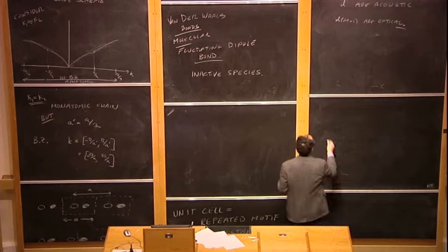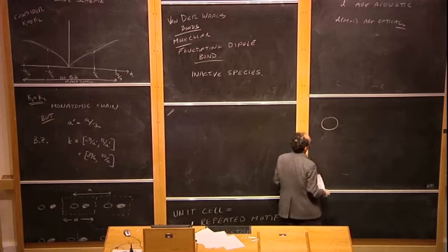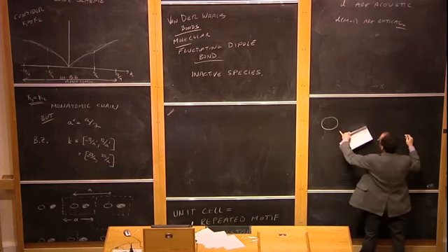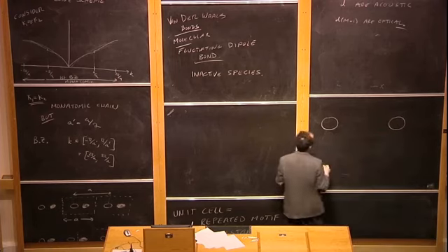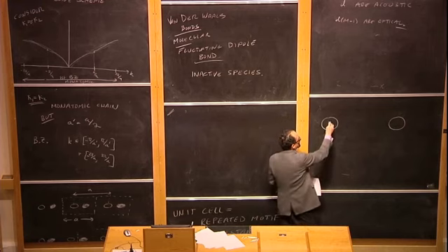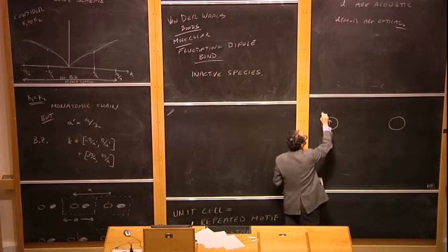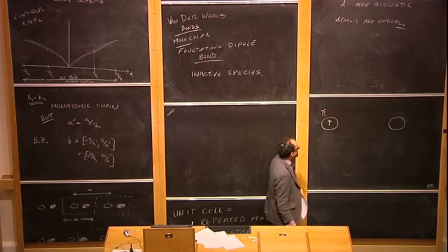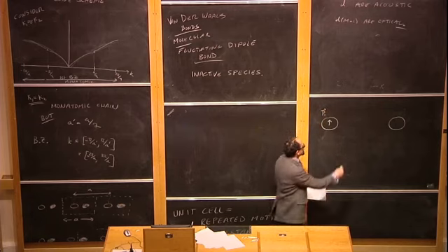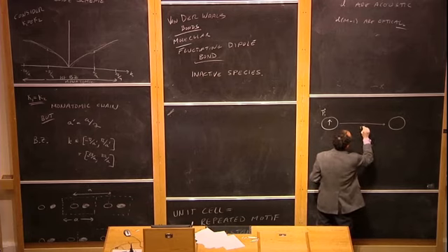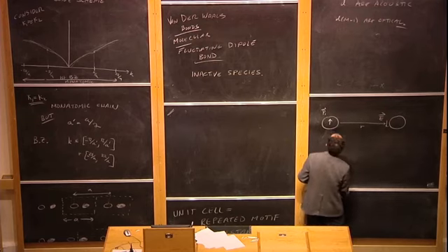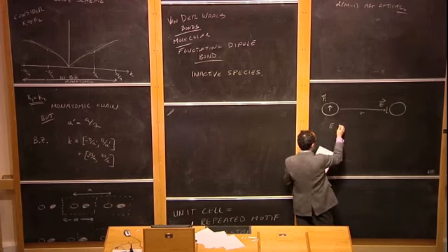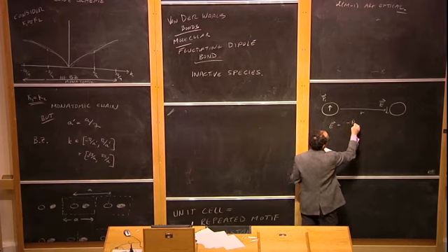The way the bond occurs is as follows. Imagine that you have, say, a nice noble gas atom over here, and maybe another nice noble gas atom over here. And suppose at some moment this atom has some dipole vector P1, a polarization. Now, if you remember from your E&M, a distance r away, there will be an electric field due to that dipole moment, in this case pointing in that direction, and E will be equal to minus P1 over 4 pi epsilon naught r cubed.